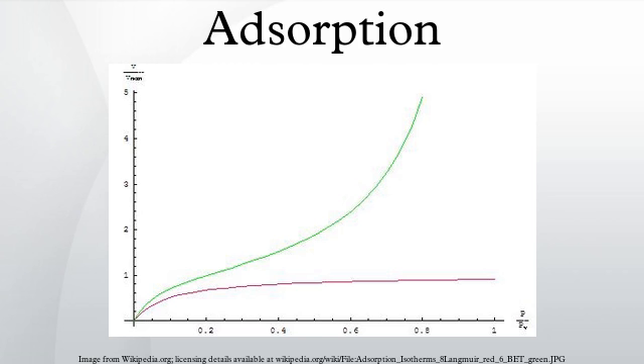The carbonized particles are then activated by exposing them to an oxidizing agent, usually steam or carbon dioxide at high temperature. This agent burns off the pore-blocking structures created during the carbonization phase and so they develop a porous, three-dimensional graphite lattice structure. The size of the pores developed during activation is a function of the time that they spend in this stage. Longer exposure times result in larger pore sizes.